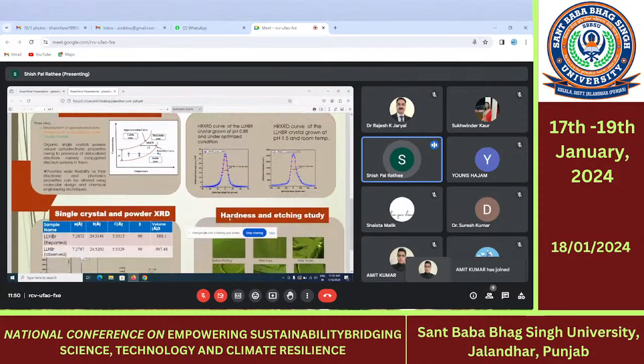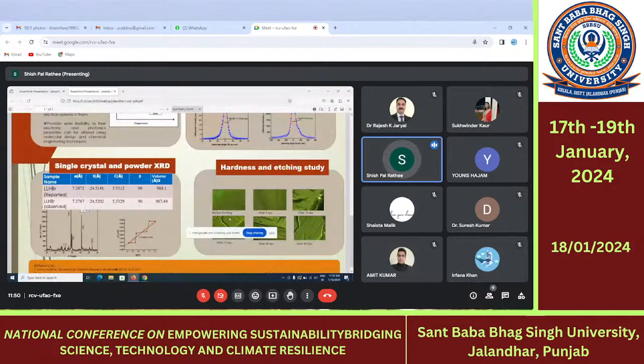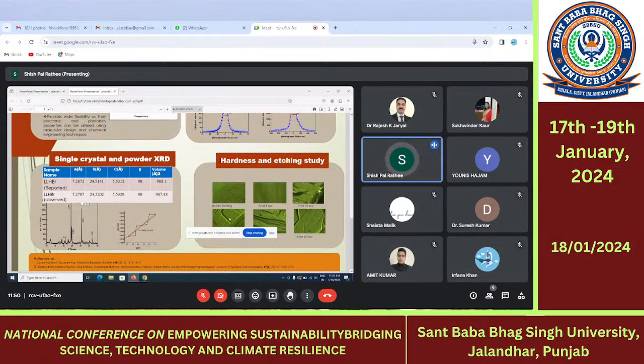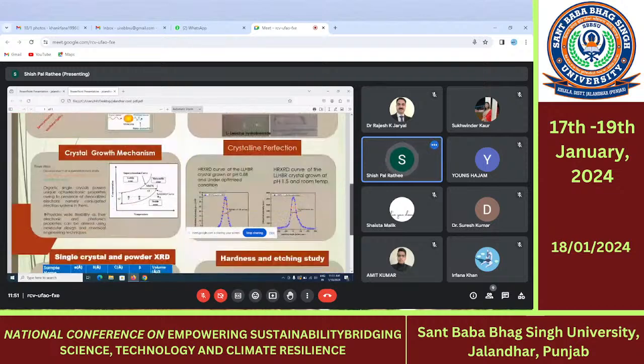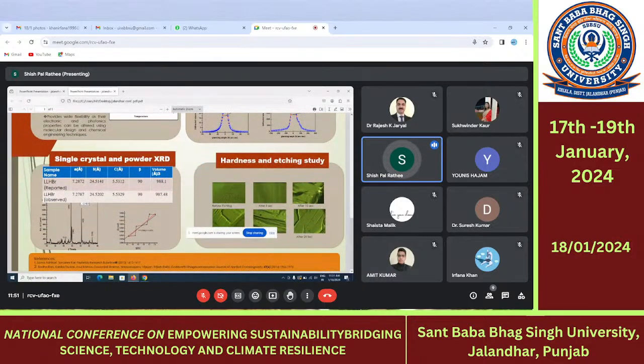And here, this is the hardness and etching study. The hardness was also studied, and these are some micro pictures from the Vickers microhardness microscope, and these are used for each. Before etching, the crystal surface lies like this. After 5 seconds, this looks almost plain, and after that these hillocks were also observed at different times of etching. Etching is just the reverse process of the crystal growth. As in crystal growth, nucleation starts and the atoms get close to each other to form the crystal, and etching is its reverse process.